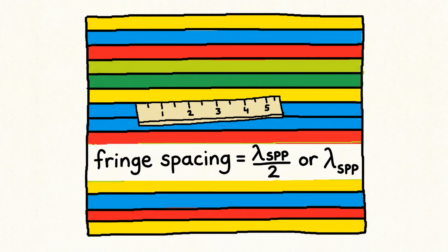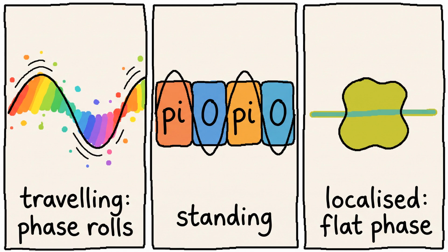A localized plasmon shows isolated bright spots, confined to corners, gaps, particle tips. No propagation, no fringes. A Fabry-Perot mode shows a clean standing wave across the cavity, bright antinodes and dark nodes fixed in space. A guided mode shows fringes too, but the field is buried inside the dielectric film and decays into the air above it. An LC resonance shows a closed current loop, an electric field maximum across the capacitive gap with magnetic energy circulating